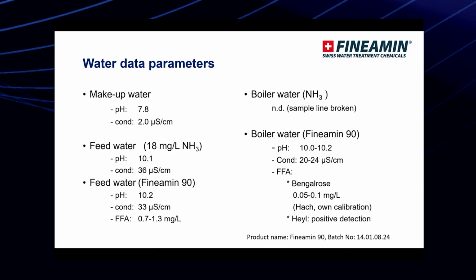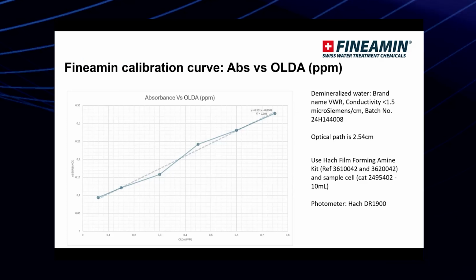We also used the Hach test kit just for semi-qualitative detection, and it is a positive detection. We did our own calibration curve based on absorbance versus the OLDA as active. So we use our own calibrations, and the optical path is about 2.54, 1 inch. We use the film-forming amines reagents, and also have sample cells, and we are using DR 1900 as a photometer.